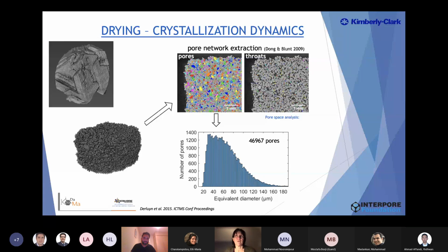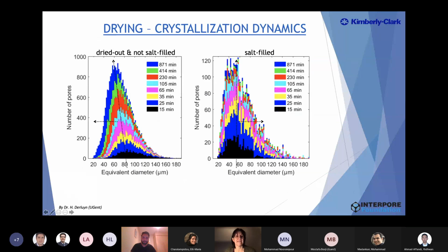Then you get a denser zone and brighter areas, and you can do this for each individual pore and pore throat or location. This allows you to say which pores, at which dimension and at which time, start to dry out without being filled with salts, and which are being filled with salts. So you can get really quantified and detailed information based on your experiments.